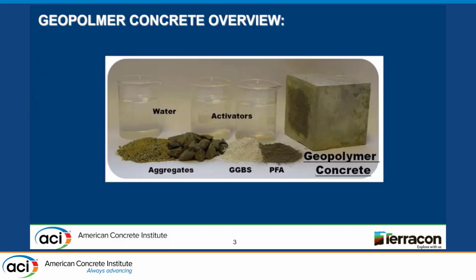Geopolymer concrete is a sustainable concrete, a mixture of an aluminum silicate source, such as fly ash, slag, or metakaolin, mixed with an activating solution. I call this material a lazy material, so usually we need an activating solution to help the reaction get started. The most common activating solution is a mixture of sodium silicate, sodium hydroxide, and water, if we need a higher water cement ratio,